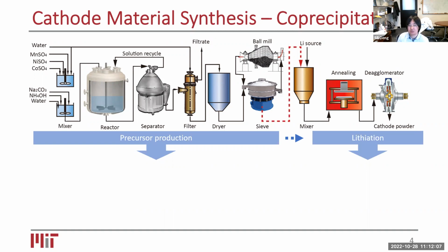It can be broken into two components, the precursor production part and the lithiation. In the precursor production part, all the transition metal precursors in the form of salt get dissolved, and then in the reactor, by controlling the pH, we can do this co-precipitation process. Then we filter out the particles, deal with the waste solution, and try to dry the particles and separate them. Then in the next step, the lithium source, in the form of lithium salt, gets mixed with the residuals from the previous step. The second step is the solid phase mixing, which, as you could imagine, the mixing and the diffusion could be very slow.